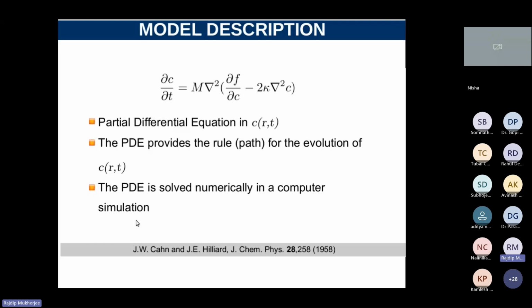So the solution of this diffusion equation, or the Cahn-Hilliard equation, is the background of the MICRESS software where it is running. It is solving this simple equation where we also need to integrate the bulk free energy from the CALPHAD system, and the diffusivity data also from the CALPHAD approach we can get using DICTRA, and this interfacial energy can be obtained from the literature or from atomistic simulations.